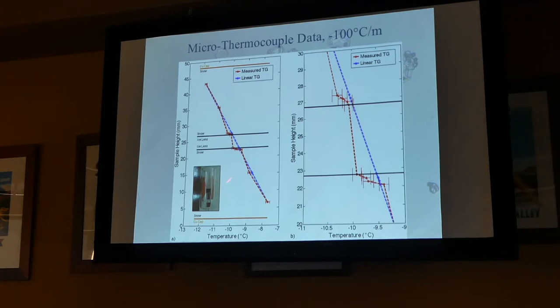In this plot, the blue line is what we imposed on the sample. This is like a 100 C per meter temperature gradient, which is pretty strong, but it takes time to do these things, so we want things to happen quickly. But in the red is what we measured. So what you see here is a much stronger temperature gradient right above and below, which I blow up on the other side. Even though we were only imposing a 100 C per meter temperature gradient, what we saw was about a 300 C per meter temperature gradient above and almost a 600 Celsius degree per meter temperature gradient below. So factor 3, factor 6 greater than what we imposed, which is really high, right?